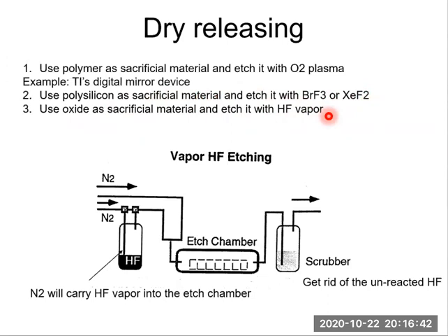Please note that we typically use an HF solution to remove the sacrificial layer. Right? That's a wet process, which can lead to stiction. But if we use HF vapor, then we can avoid the stiction. This figure shows the simple setup for vapor HF etching. We use nitrogen gas to carry HF vapor into this etch chamber. So the devices or wafers inside this chamber are etched by HF vapor. So this is a dry releasing process, which can avoid stiction.